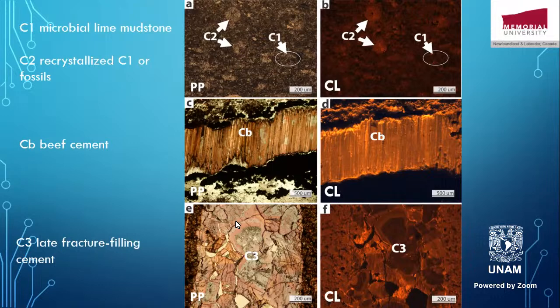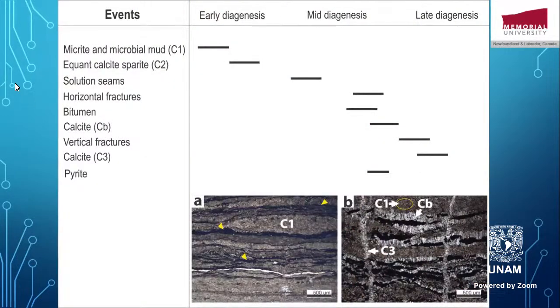We have them all shown here, under plane polarized light, and here under cathodoluminescence. Of course, C1 seems dull, beef cement very bright, and C3, which is the latest calcite fracture filling cement, you can see it shows zoned cement. This is the paragenetic sequence. As you can see, it starts with calcite dissolution, horizontal fractures, bitumen, then the beef cement opening fractures, and the horizontal fracture of the beef cement, then the vertical fractures and the latest calcite cement, which is C3, followed by pyritization, submarine pyritization.